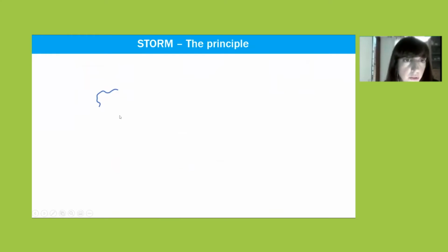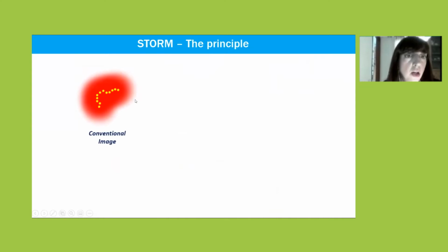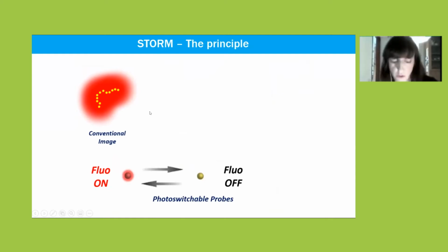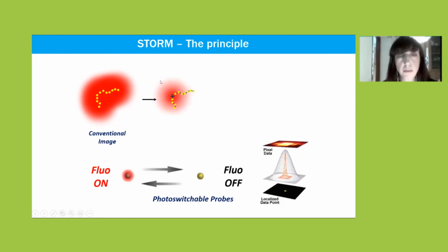So if you have your structure of interest labeled with fluorophores, in a conventional image, all of the fluorophores will shine at the same time. So then you will just see a very blurred image. The trick of super resolution microscopy, of single molecule localization microscopy, in this case is a STORM. Many acronyms are used depending on the specific technique. In a STORM, what you do is you use a trick to have the fluorophores in a photoswitchable way, so that most of them are in the off state and only few of them are shining. Because only few of them are shining, around 1% of the total, then you are sure that you can fit a Gaussian on the emitting signal and then have a localized data point.